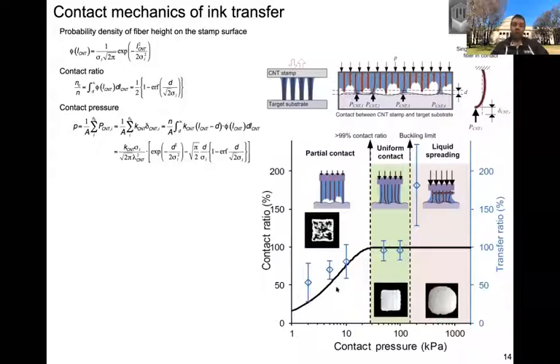And we worked out a relationship between the contact ratio, i.e. the fraction of the stamp area that's in contact, and the amount of liquid transfer, and you have a region of contact pressure, i.e. force per area, over the CNT pillar or CNT stamp, where you get good liquid transfer. And there's more on this in a paper in Langmuir that we published just last year.